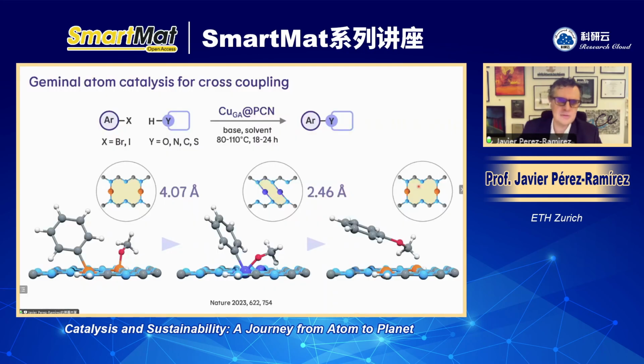And so what these geminal atoms allow actually is to make very complex organic synthesis possible. This organic synthesis, this is a cross-coupling family of reactions, which will be completely not happening if the copper atom will be only just one isolated. They run very efficiently in geminal atom form, because upon a coordination of the reactants on the neighboring copper sites, and again, the resting distance is the ground state distance, stable distance is about 4 angstrom.